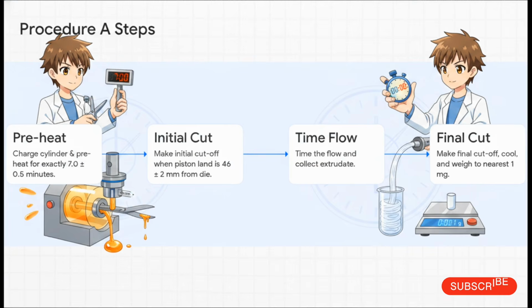The whole sequence requires exact timing, especially that strict 7-minute preheat to soften the material without causing thermal degradation. Heated too long, and the plastic chemically degrades. Too short, it won't flow. The operator actually has to wait until the piston is exactly 46 millimeters above the die, make an initial cut to ditch the preheat material, start a timer, and then make a final, perfectly clean cut to collect the test sample.